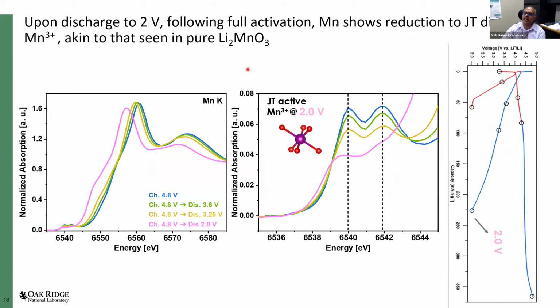So, in order to understand this, we can look at it while discharged. And here we are looking at the sample at a fully discharged state at 2 volts. And clearly, although there was no electroactivity of manganese during the charge, during full discharge, when you bring it back to 2 volts, there is a large shift in the edge and a large change in the pre-edge, which is all clearly showing that the manganese reduces. Analysis of the XAFS shows that we need a minimum of 2 manganese-oxygen bond distances and 2 manganese-manganese or manganese-transition metal distances, clearly showing that we are forming Jahn-Teller distorted manganese 3 plus, which again, because of the large distortions that is associated with manganese 3 plus, is not good for a cathode material which has to be repeatedly cycled.